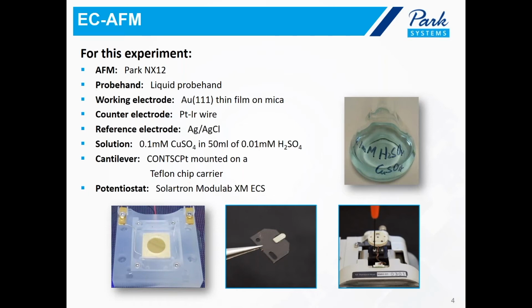Here in the experiment, a silver chloride electrode was used as reference electrode since a chloride solution was not used. So in case you will use a chloride solution, other types of electrodes such as mercury or mercurous sulfate can be used instead. And for the platinum iridium electrode, we selected this one as a counter electrode since this material is chemically stable. Therefore, it will not contaminate the solution.